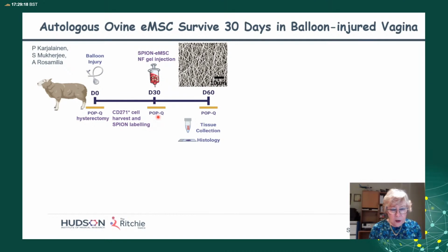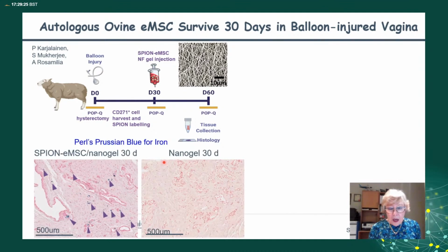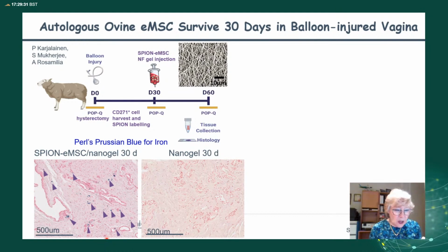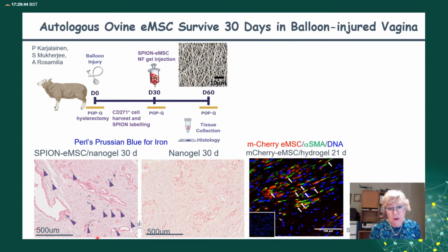Day 0, day 30 they got their own cells, and then 30 days later we did the histology. And this shows here the EMSC treated cells. We detected them using the Perls Prussian blue to pick up the iron oxide of the nanoparticles that they'd ingested. And you can see the cells quite spread around near one of the injection sites, and sometimes around blood vessels where you'd quite expect them. None ever observed in the nanogel alone.